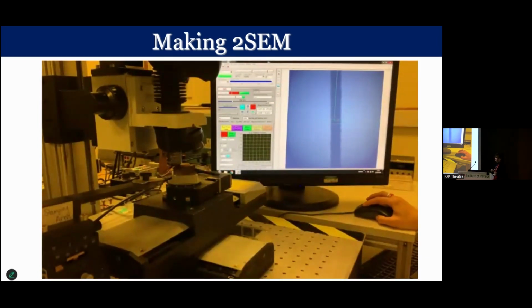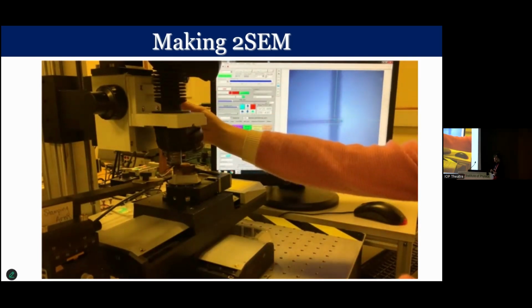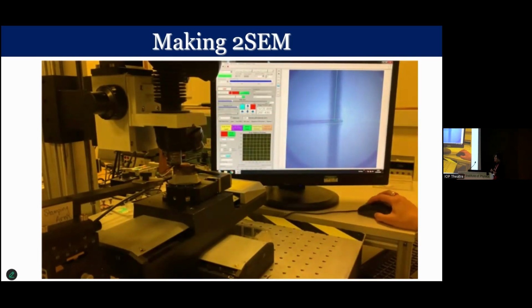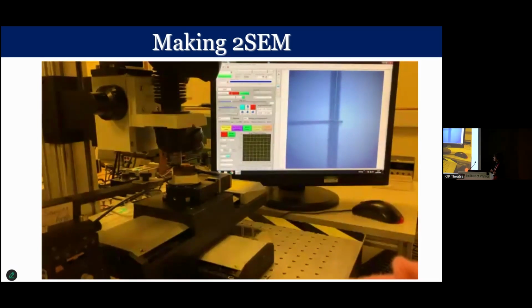Which means we can use a similar technique to build vertical structures of 2D materials, just like a slightly more complex version of Lego. Once we bring the graphene into contact with the surface, it sticks to it via van der Waals interactions, which are stronger than the sticking force of the needle, so that when we retract the tip, the graphene is left on the surface of the substrate.